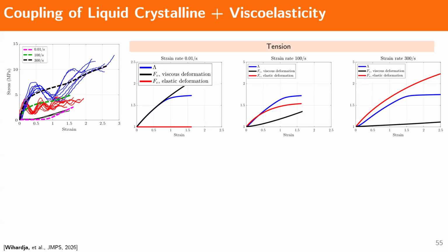We can get more physical insight into what's happening in this material by looking at the evolution of the internal variable. In particular, our internal variable can be physically linked to some physical quantity. Lambda here is an indication of our spontaneous deformation, a descriptor of the spontaneous stretch in the mesoscale. As we go to higher and higher strain rate, lambda, our spontaneous stretch, gets more and more suppressed. And then Fe here, which is the elastic instantaneous response: at low strain rate, the polymer is allowed to relax completely. But when you go to higher and higher strain rate, you get larger and larger elastic resistance in the polymer when we first load it.